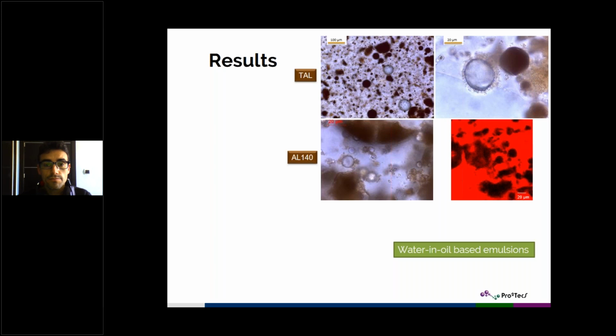As you can see, we have water droplets that are surrounded by that acetylated lignin for both the conventional acetylated lignin and the acetylated lignin obtained by microwave-assisted acetylation. We can see by the confocal microscopy that our continuous media is the castor oil, while the water droplets are just in black. So the continuous media is oil, and the water is just forming the emulsion.